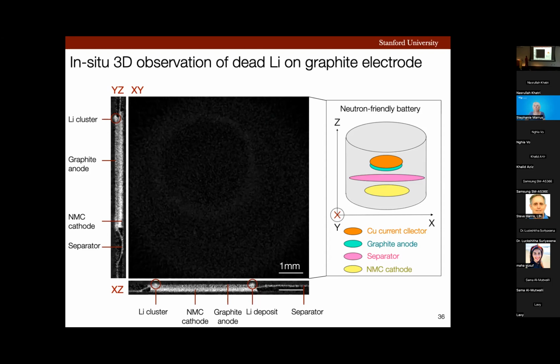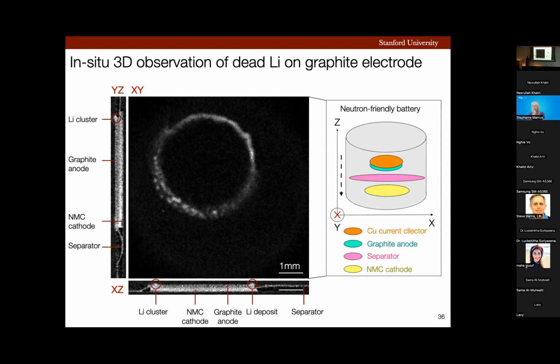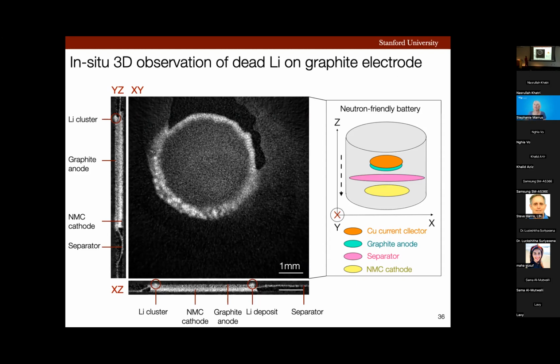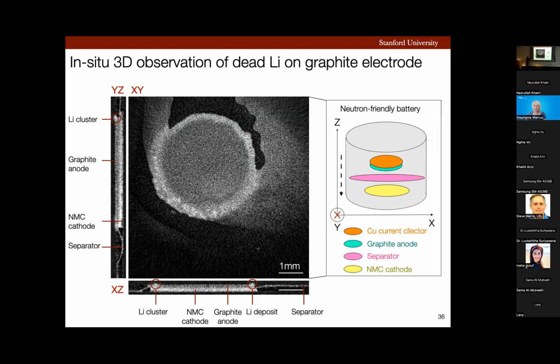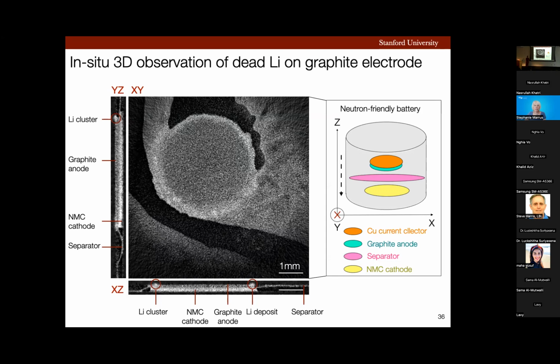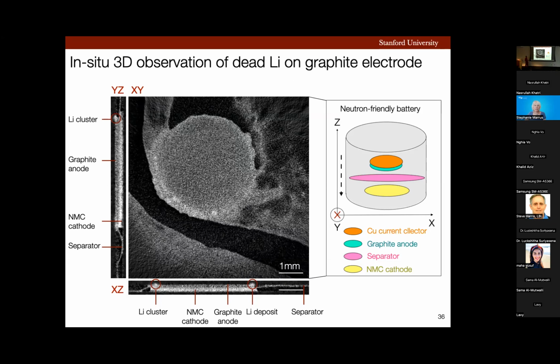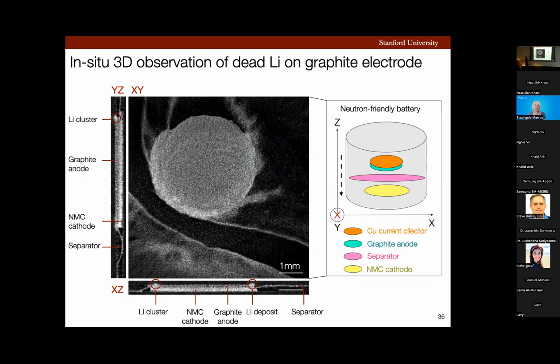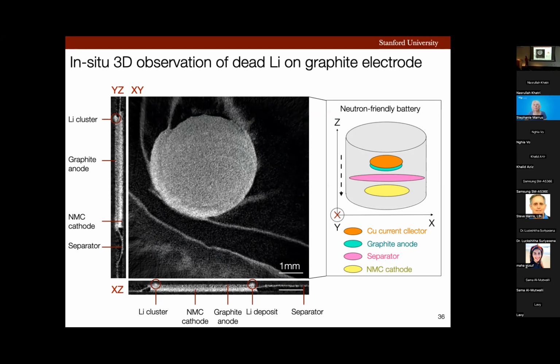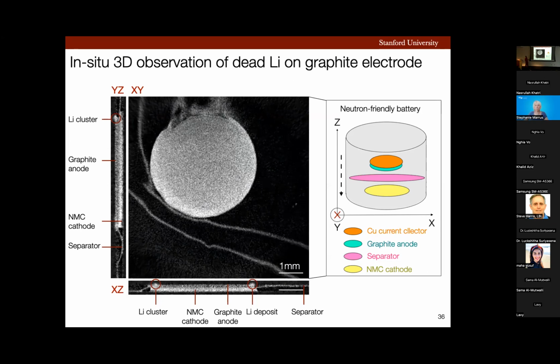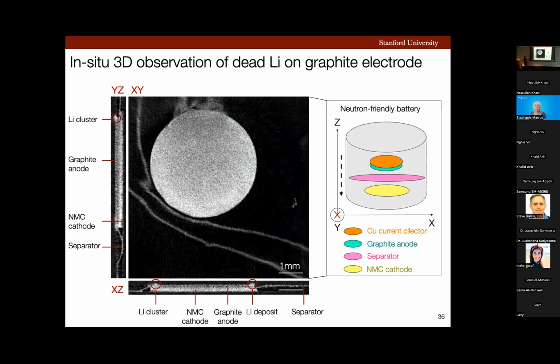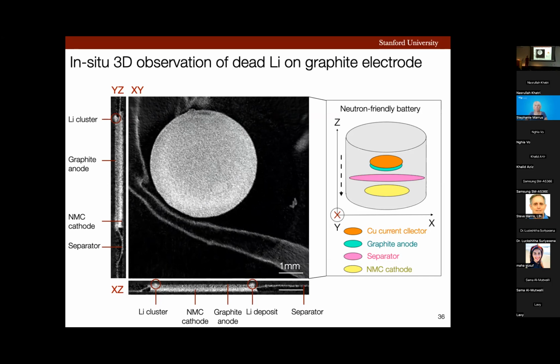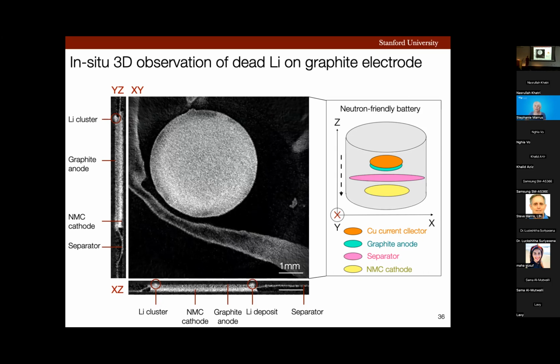Now, in this video, we are going from the copper current collector towards the cathode. These brightish deposits, as you can see, they are at and around the edges of the graphite anode, which means those are the regions that are most susceptible to forming lithium. Now we will start seeing this graphite anode in the middle. We have also started seeing this separator. Separator is a very thin membrane, which is usually placed very flat during battery making, but its undulating surfaces or some crevices do get picked up in a micron scale imaging, which we can see in the form of these structures in this image. And this brightish cluster you can see corresponds to plated lithium. Now we are going on the other side of the separator, and we'll start seeing this NMC cathode as a round, punched, big disk. Okay, this data clearly shows in situ 3D observation of dead lithium on graphite in a full cell battery.